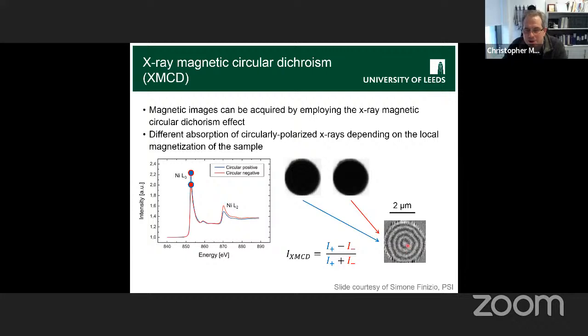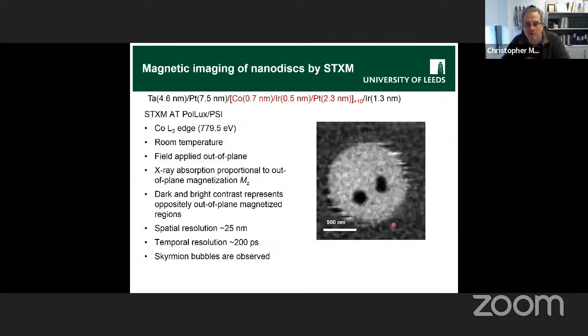So what you can do is image the Z component of your magnetization, and that's very useful for seeing these skyrmions. So here's again one of our first examples. There's a 1 micron disk of platinum, cobalt, iridium multilayer with 10 repeats. And you can see most of it's magnetized one way, but there's these two little patches that are maybe a couple of 100 nanometers across or a bit less. And they're magnetized the other way. So there are a couple of skyrmions existing inside this disk. This one's pretty circular. This one's actually slightly deformed. So we're looking at the component of the magnetization that's in or out of the plane. Then around the edge of this, we'll have these in-plane moments that give us the Néel skyrmion.